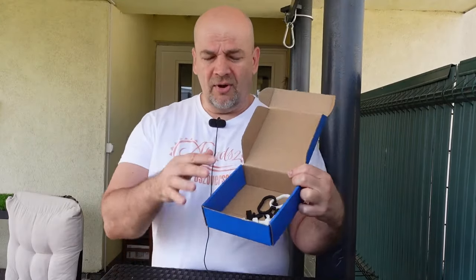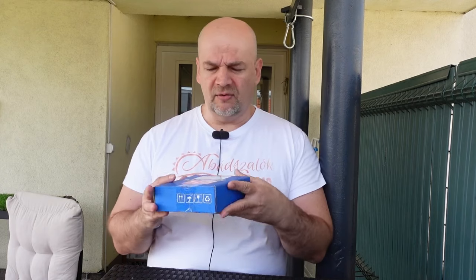And now the conclusions. Well, very interesting materials, and I have to learn more about them so I can choose the proper one for my applications. And my favorite property of the nylon was that horizontally or vertically printed ones have almost equal strength, so we don't have that weaker layer adhesion effect. With the nylon, I know about its creeping properties, but actually it stopped with the creeping on the 3rd day. But I was surprised that after I placed it in the oven at 45 degrees Celsius for 1 hour, it had some additional creeping. Anyway, as I mentioned, very interesting materials.